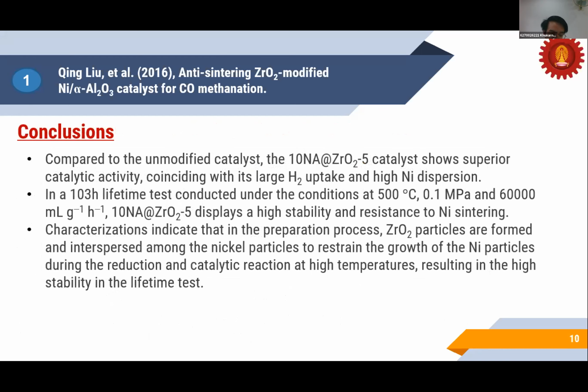Conclusion: in a 103-hour lifetime test conducted under present condition, 10NA@ZrO2-5 catalyst displays a high stability and resistance to nickel sintering. Characterization indicates that in the preparation process, zirconium oxide particles are formed and interspersed among the nickel particles to restrain the growth of the nickel particle during the reduction and catalytic reaction at high temperature, resulting in the high stability in the lifetime test.